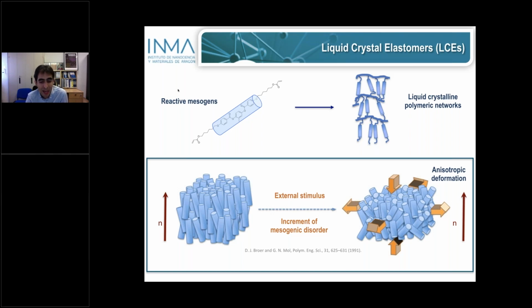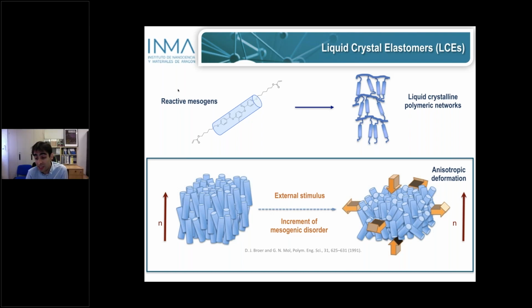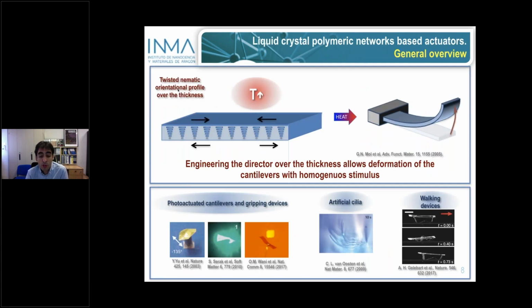And why does this happen? Well, this increase of temperature produces molecular disorder in the system, and as a result, these elongated rods get disordered, get more oblique angles with respect to the preferential orientation direction. And due to the linkage of these molecules to the polymeric network, this disorder induces a contraction of the material in the preferential orientation direction and an expansion in the orthogonal directions, as we see in the bottom part of the slide. And this is a key aspect that will appear more times now.